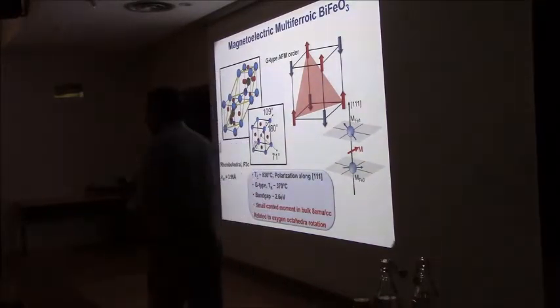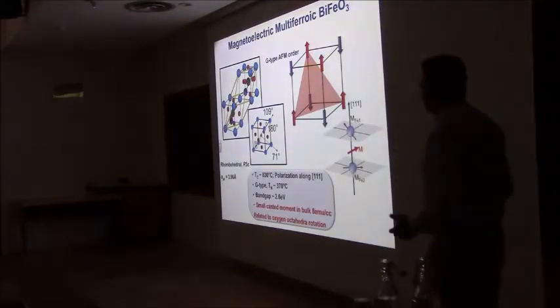Now it's very common. If you don't use correlations, as all our theory colleagues talked about, BFO comes out to be a semiconductor with a very small band gap. You have to put in the correlations to get the band gap of 2.6, 2.7. This is a very complicated system in that sense. From a ferroelectrics perspective, it's relatively well behaved. The polarization is pointing along this direction.